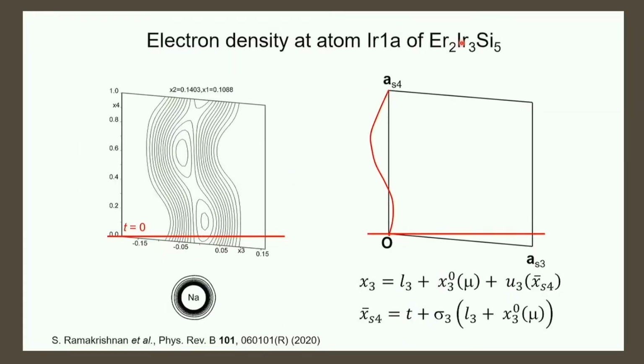So here for the erbium iridium silicide modulated compound, you see an iridium atom at its position x1, x2, and the x3 or z coordinate is here, and the fourth coordinate is vertical, now starting at 0 at the bottom and 1 at the top. So the periodicity is 1, it counts the periodicity, so 1 means 1 wavelength, and then this figure continues periodically. And what you now can do is take physical space at t equals 0 and then shift it by increasing t until t equals 1. There we are.